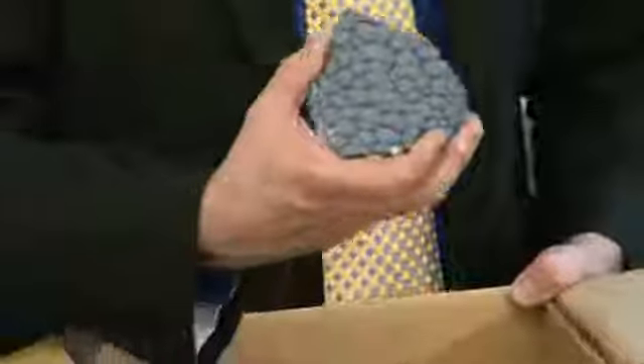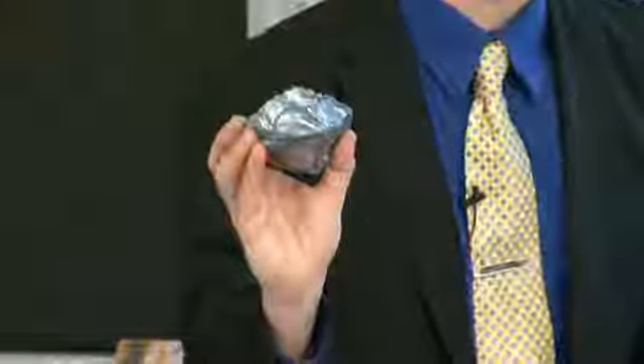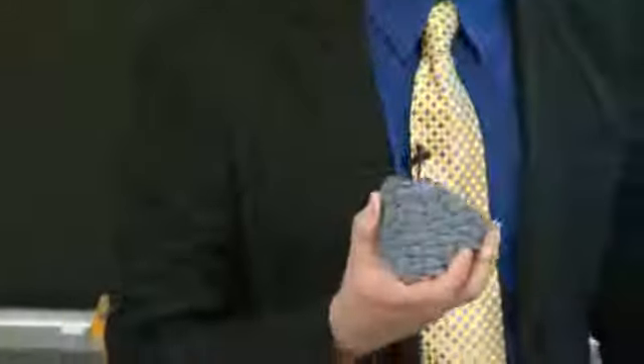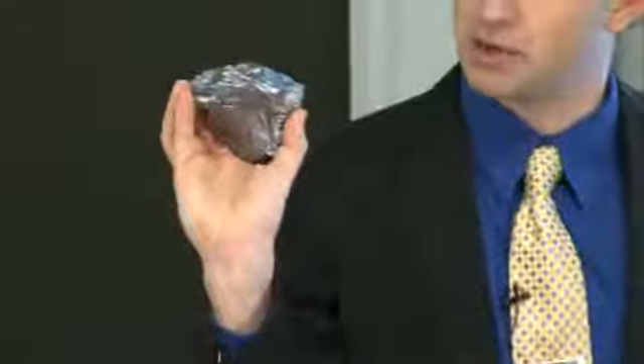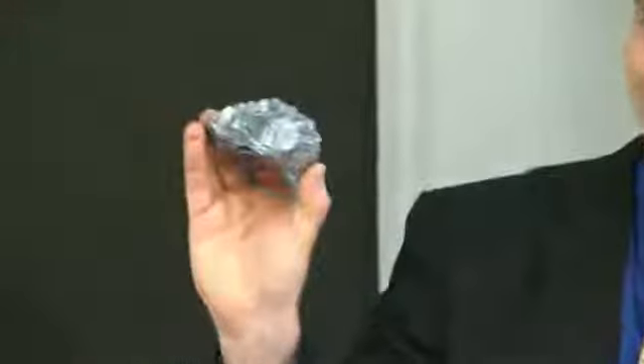But in general, if you're just trying to crack it up and break it into a smaller piece, into a chunk like this, and throw it into a big ingot furnace, it doesn't really matter what the surface looks like. On the inside, it's pretty dense silicon. And if you look very carefully, right in the middle there, you can see the rod, the initial seeding rod. It's a slightly different color. So I'll pass these around, and please be gentle.